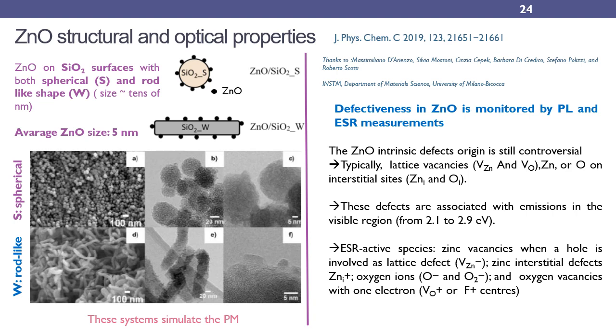Photoluminescence and electron spin resonance measurements have been conducted aiming at the understanding of the role of the zinc oxide intrinsic defectiveness for the stabilization of the phenol radical. As it will be explained by Roberta Crapanzano, zinc oxide is known to be rich in intrinsic defects, like oxygen and zinc vacancies or interstitials. These defects are responsible for the luminescence behavior of zinc oxide. Moreover, some defects give rise to ESR species, like singly ionized zinc and oxygen vacancies, as well as oxygen ion.